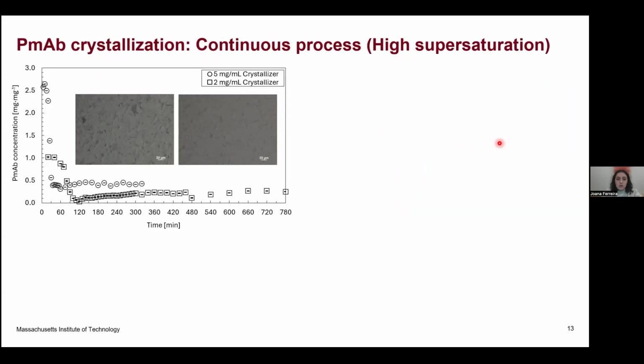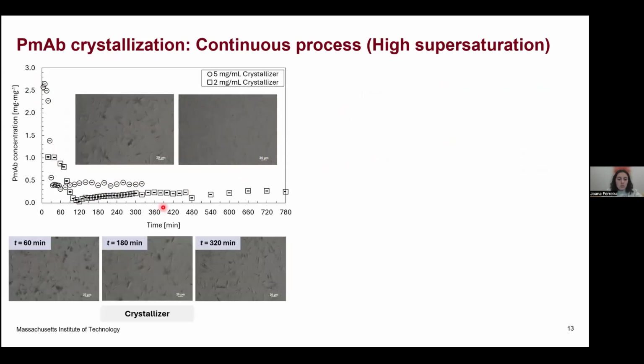So for the run at high supersaturation, the 5 milligrams per milliliter, we can see that it does not take a lot of time to observe a drop in the concentration because of the high supersaturation. So the tendency is always to see some aggregated crystals, while for the run at 2 milligrams per milliliter, we see some nicer, more dispersed crystals and longer. But it's also nice that with the offline sampling strategy, we can see the tendency of the growth over time. So initially, after the batch run, we tend to see some aggregation, but then over time it gets suppressed because of the drop in the concentration, where we are mostly promoting growth.